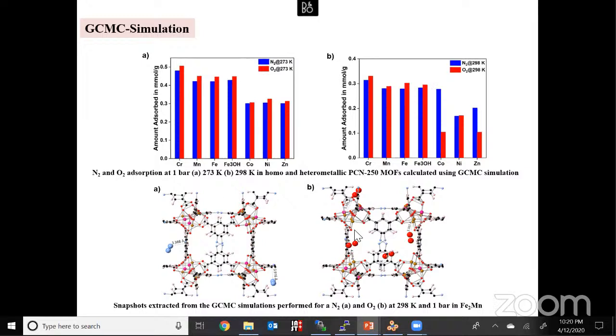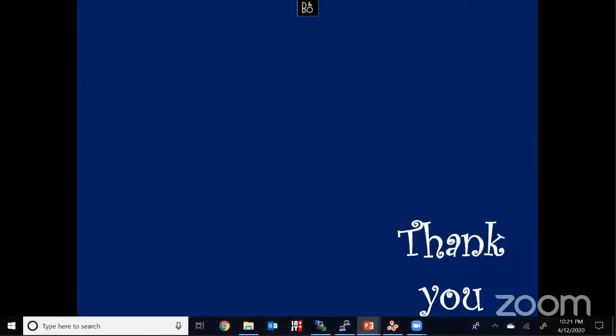And the simulation snapshots also show that the nitrogen molecules always try to populate over the linker atom, and the oxygen molecule tries to populate over the open metal site. So from this study, we found that if you have a heterometallic moiety, it will be highly helpful to selectively store oxygen over nitrogen. This kind of model study will be highly helpful to people working in this area, and to experimentalists to selectively synthesize that particular material for that particular application purpose. Thank you for your kind attention.